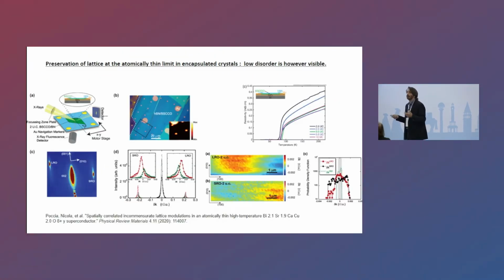Now, there is something that you have to preserve when you do that. First of all, it's very remarkable. This is an X-ray mapping done with a 50 nanometer beam on top of a very thin BSCCO crystal, and you see the superconducting transition temperature. In this right corner, you see a histogram, and you see that the variation, the sigma of the K-space order of the superlattice modulation in the very thin limit, is only 0.002. So this means that when you go to the very thin limit, the incommensurate modulation that we have heard about before is really stable, is there, and doesn't change at all, or changes very marginally.